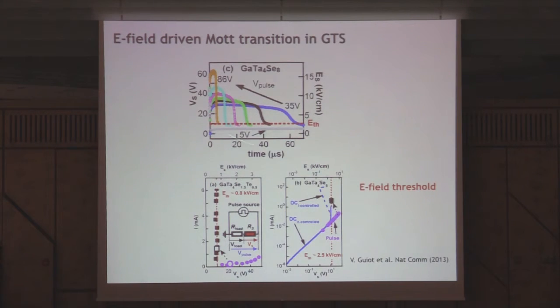Okay, so you do this now in a systematic fashion, and you apply voltage pulses of different intensities. So here you have voltage, and you see that the transition occurs faster and faster as the voltage is increased. So when you put this voltage versus current on this plot, you see that this is the initial branch, the high resistance branch. So you apply a voltage pulse of this magnitude, and after a little while, the system changes to the other branch.